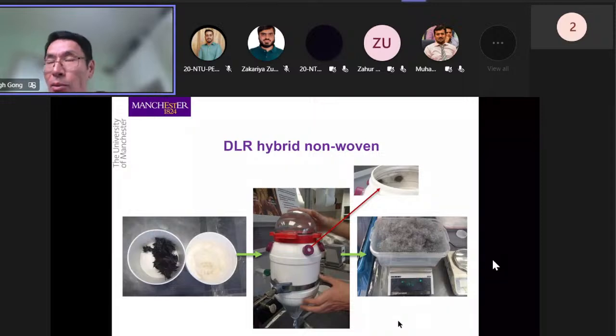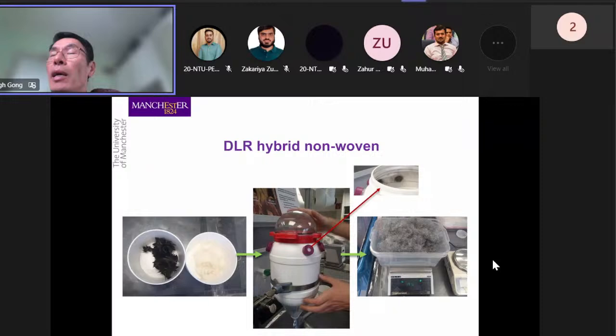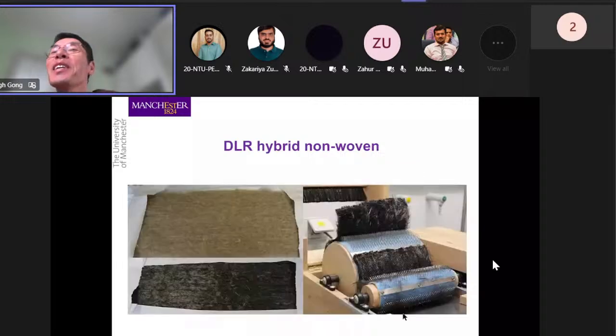Now, as I said, carbon fibers are difficult to open mechanically because the fibers are brittle, they are easily damaged, and generate lots of dust. So as you can see here, they were trying to mix it in a closed chamber manually. But obviously, we are doing research, so this is just doing trials, essentially. And then using a small non-woven rig, as shown here, is really very, very tiny.